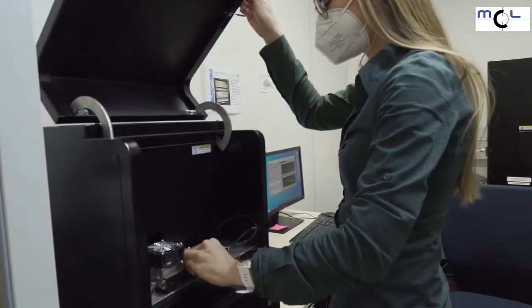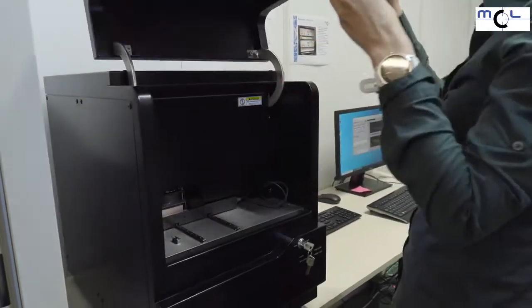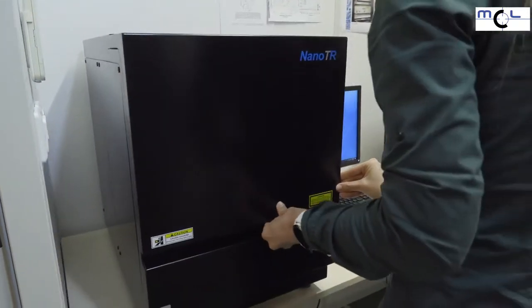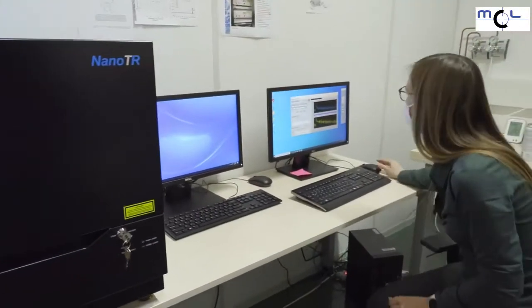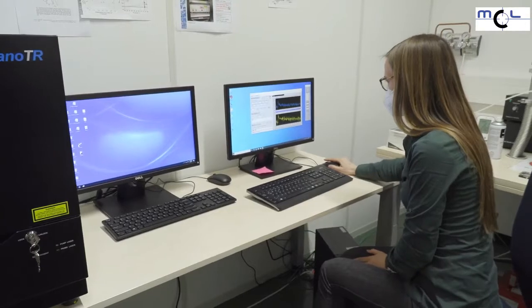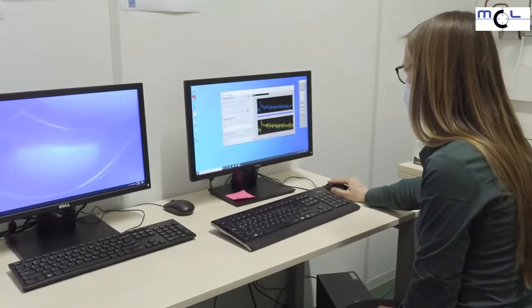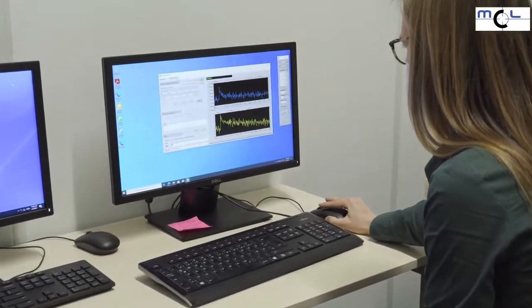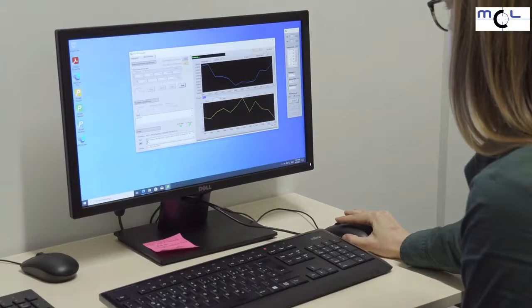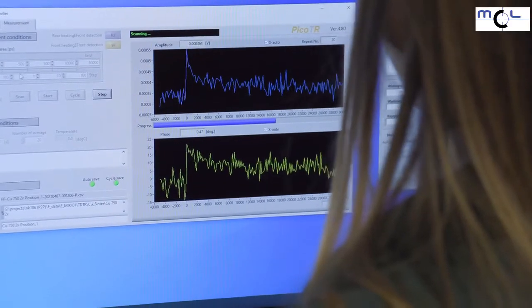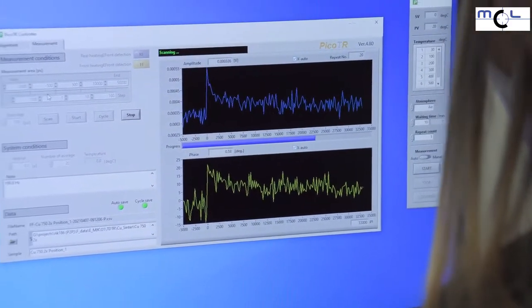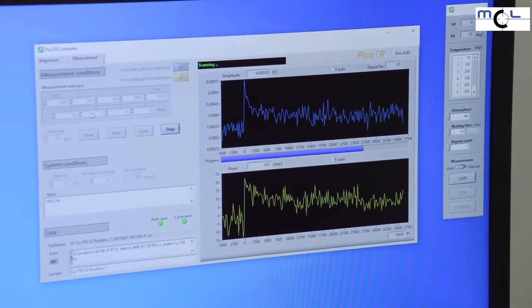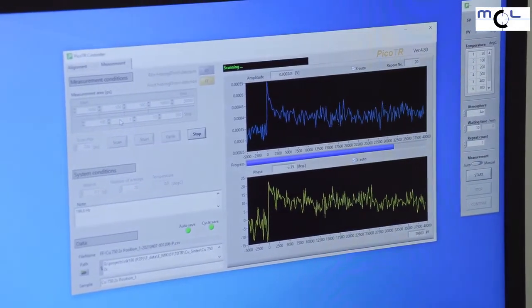In addition, the time-domain thermal reflectance measurement is an optical method where a laser is used to catch the heat dissipation through the layer system. By consecutive measurement of different layer systems, the TDTR can detect the thermal diffusivity of the individual layers and the corresponding thermal interface resistances.